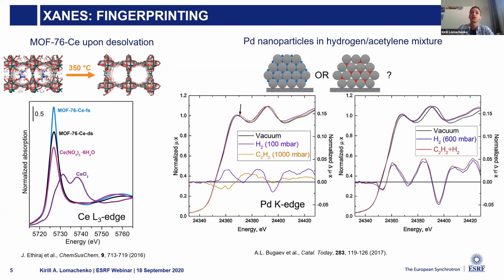Then we measure the spectra in our mixture, and we see that this resultant spectra look very much like the spectra of palladium hydride and not at all like those of palladium carbide. So we can conclude that in this mixture we have palladium hydride.